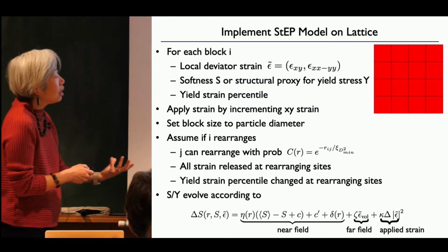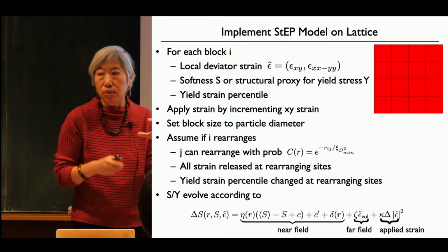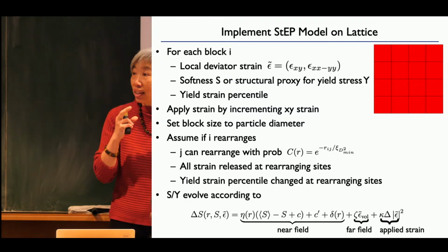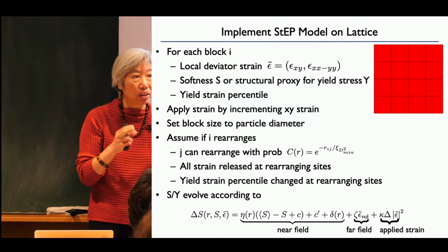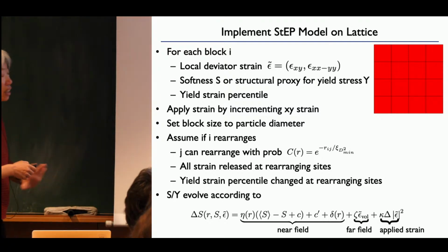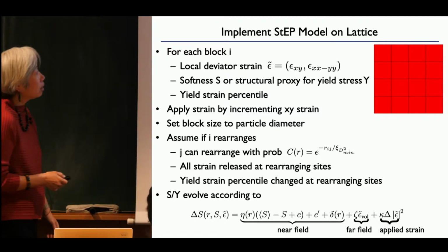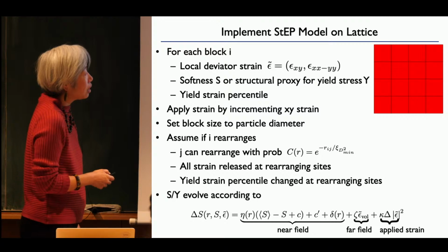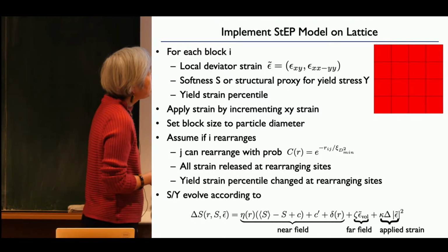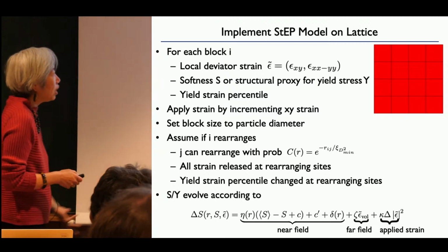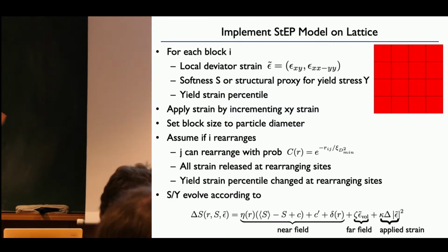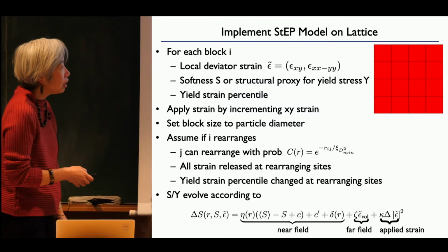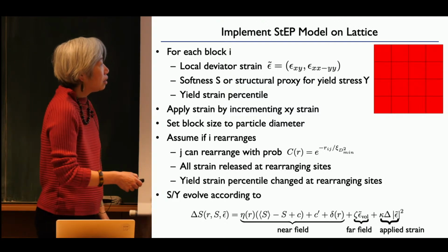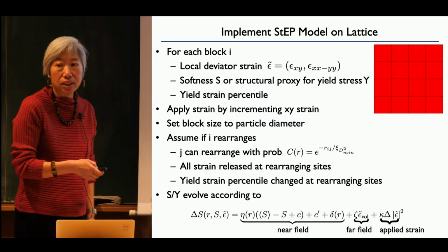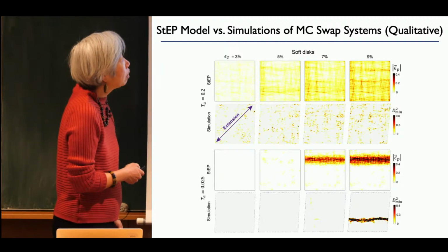And this is because, unlike elastoplastic models, which fix the block size to be the total size of the rearrangement, so it can be many, many particles, we're fixing the block size just to be one particle. So we take care of the size of the rearrangement that way. At the rearranging sites, we release all the strain, which every time you have a rearrangement, you change your yield strain percentile, and then you just let the softness evolve according to this thing that we came up with.